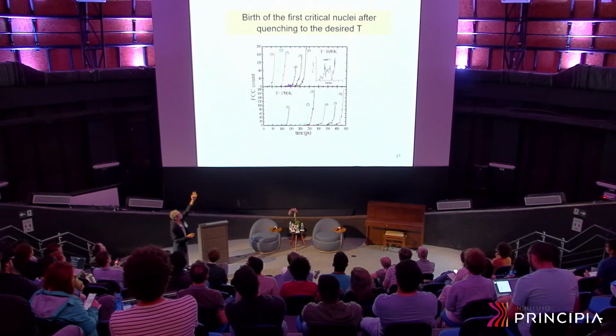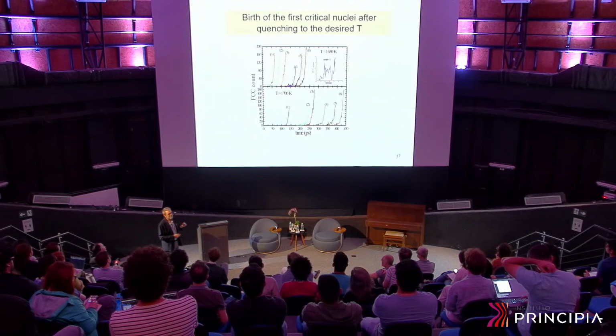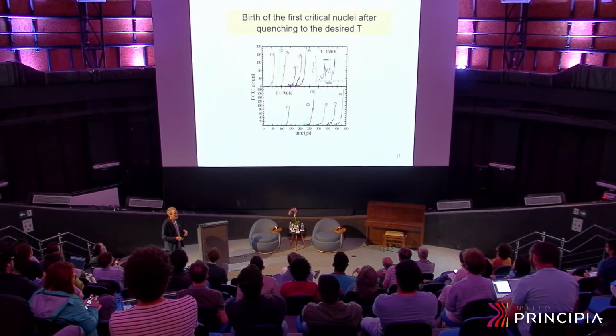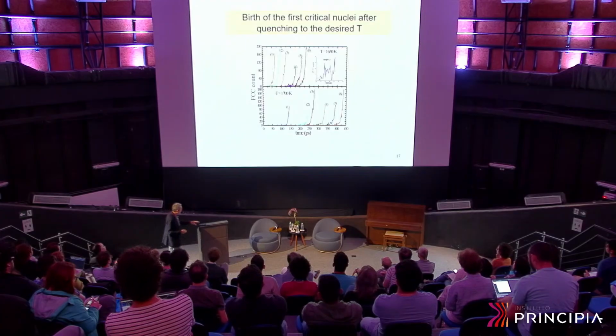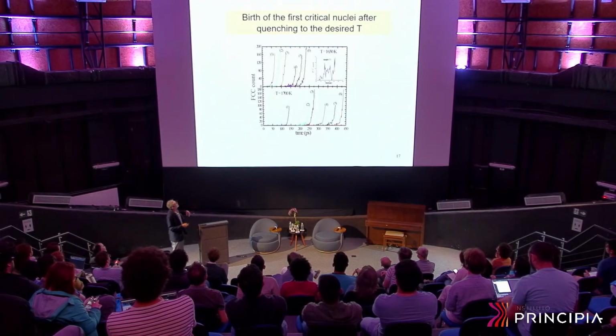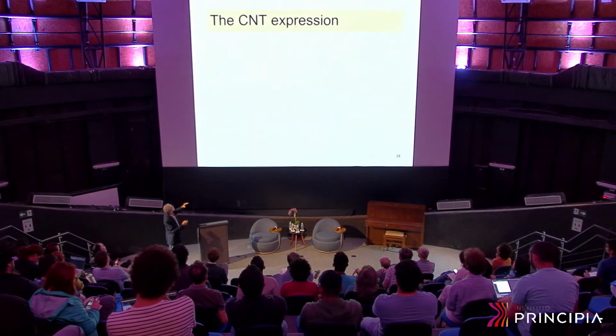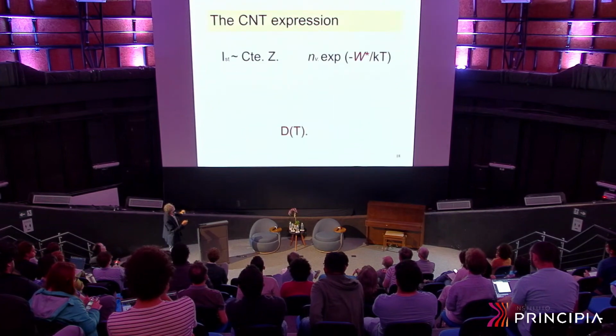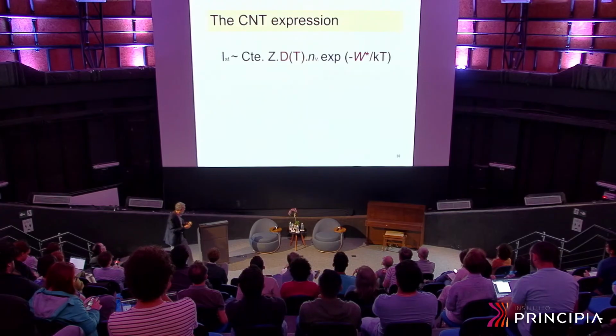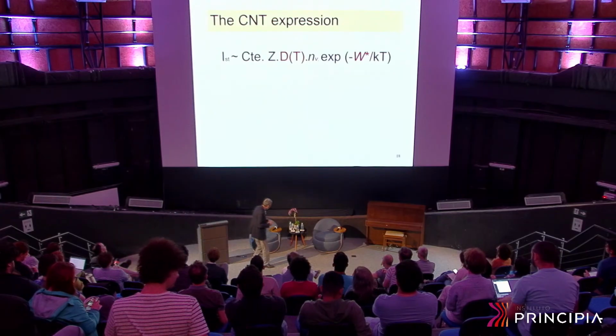By doing half a dozen experiments or so, you can compute the average time to form the first nucleus in your supercooled liquid. And then you change the temperature, you do these things again. In this way, by MD simulation, you can infer the time to form the first nucleus and the nucleation rates. But before I show you results, let me just dwell on the equation.